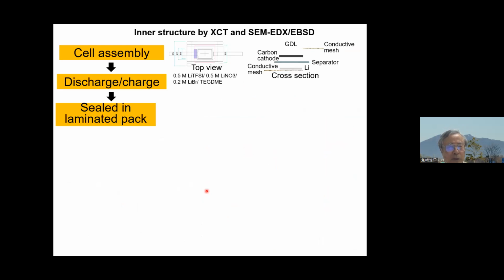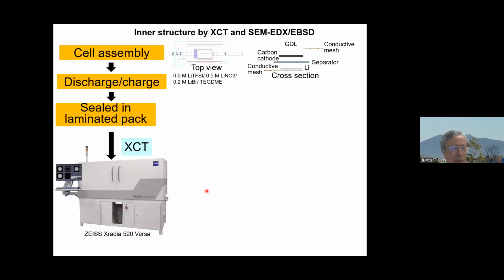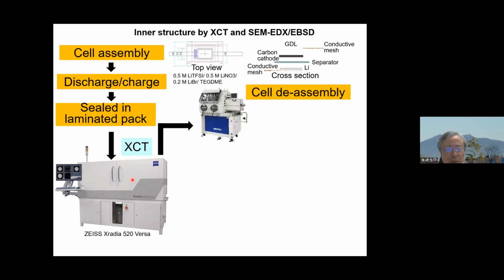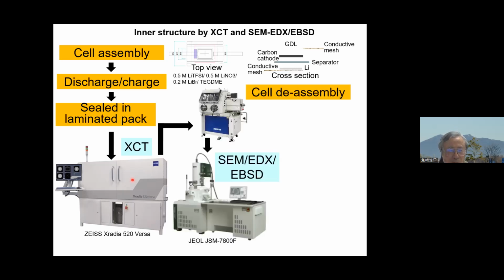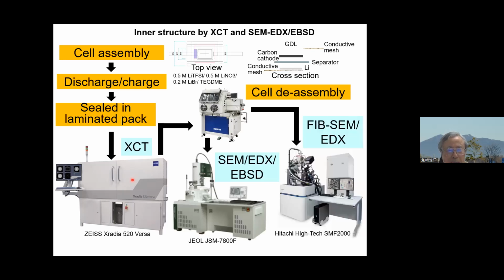So we use X-ray CT, and also after the assembly we do the SEM EDX or something. After the cell assembly, discharge charge and sealed in the laminate pack, we carried out the X-ray CT, which we don't need to disassemble. Then we disassemble the cell and go to the SEM EDX EBSD.